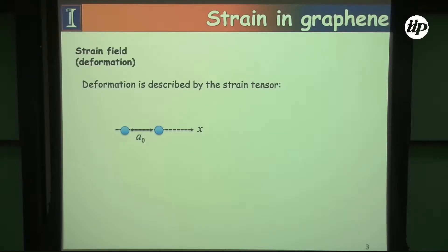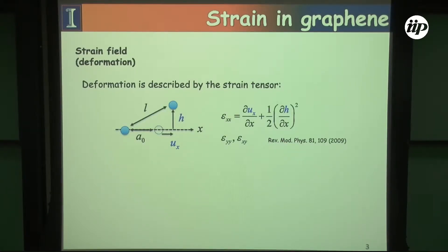The interesting thing is straining graphene. What we plan to do is take our normal lattice displacement and displace it from its normal position to something different — in particular, a vertical displacement and a horizontal displacement, both in-plane and out-of-plane. We can then calculate the strain tensor based on the derivative of the in-plane displacement and the out-of-plane displacement in the x-direction, y-direction, and the cross-directions.